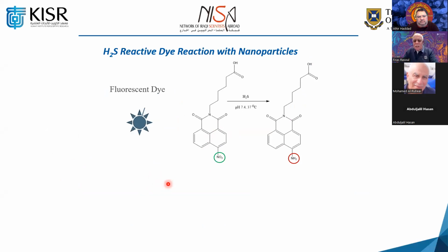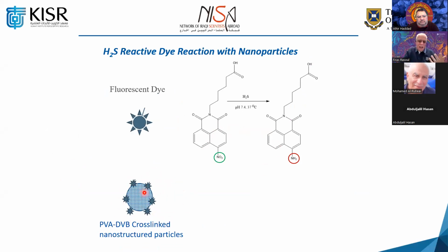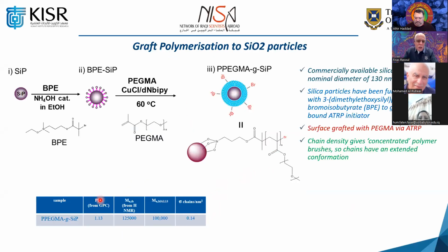Okay, so now I gave you information about this, the polyvinyl acetate or polyvinyl alcohol, after we converted it with divinyl benzene cross-linked, and we coupled this to it and we evaluated it. As I said, the difficulties from that make us think, because of the temperature, especially if you want to use it at a higher temperature level underground or somewhere else, then this might not be stable enough. So we thought, okay, why don't we use a silica nanoparticle? The chemistry is quite similar, but I will just show you now how we do it.